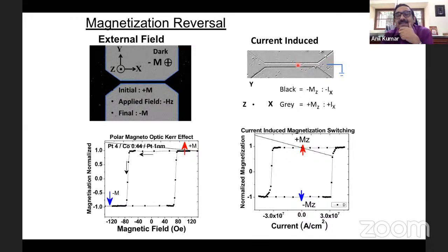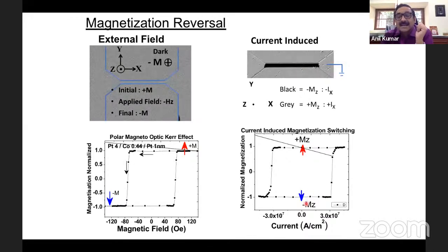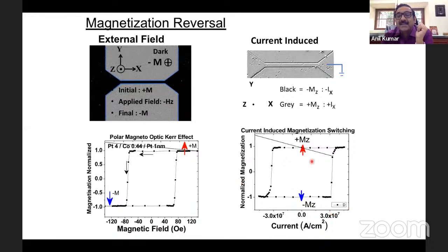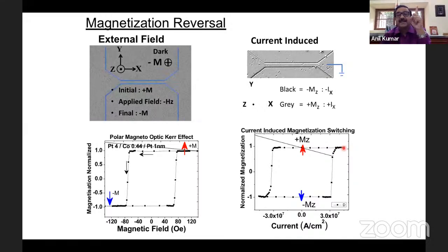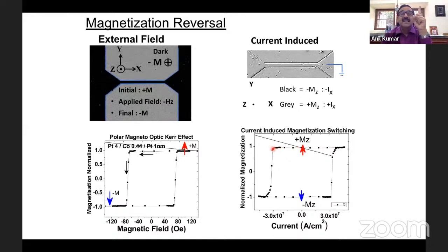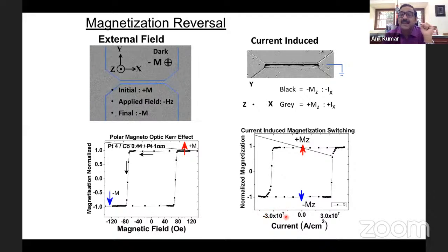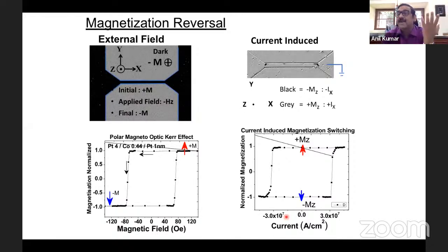Now, if I concentrate on this region, and if I plot the applied current versus the magnetization, you see that I apply an electric current, everything is magnetized upward. I reverse the current and I come to the negative current. Above a critical current, I switch the magnetization downward. And this current is called the critical current. And this critical current density in this particular case is 3 into 10 power 7 ampere per centimeter square, or 3 into 10 power 11 ampere per meter square. Already you have one order of magnitude lower critical current compared to the spin transfer torque. So this is the concept.